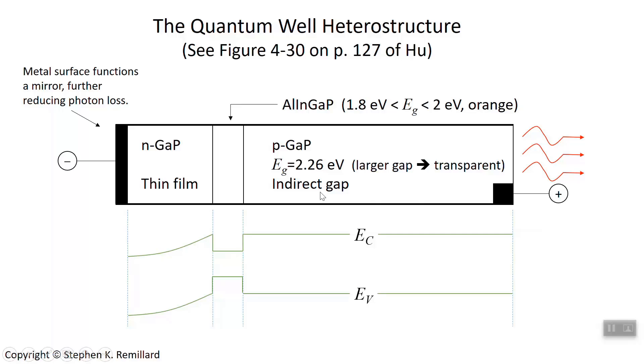The p-type is a substrate, so it's very thick. This length could be hundreds of microns, and this length is probably 10 nanometers. The conduction valence band edges on the p-side look like flat horizontal lines, 2.26 electron volts apart. Same band gap for the n-side. The band bending that happens across the thin film is there to ensure that the Fermi energy, which is close to the conduction band in the n-type material, is closer to the valence band in the p-type. The Fermi energy should be a flat line when we're not biased. With the smaller band gap, you have to draw it smaller.